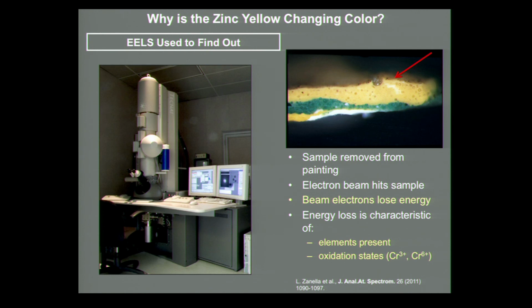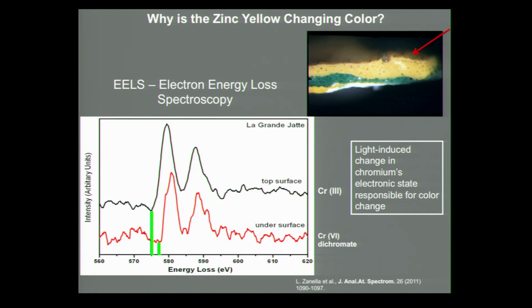And the amount of energy lost by the electron beam is characteristic not only of what atoms are present, but what their oxidation states are. And if we look at the EELS data of the top surface of the paint, which is brown, versus the undersurface, which is yellow, what you can see is that there's been a shift in the spectra. So the spectrum of the top surface is shifted a little bit over to the left versus the spectrum for the bottom surface.